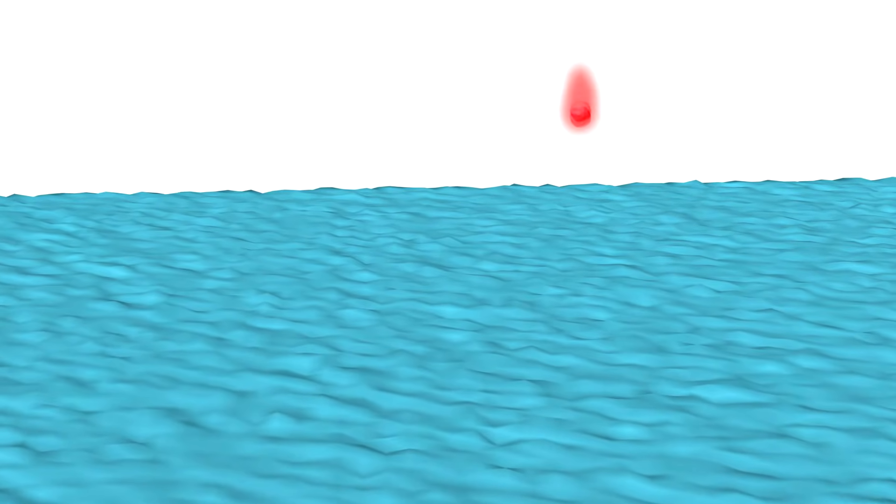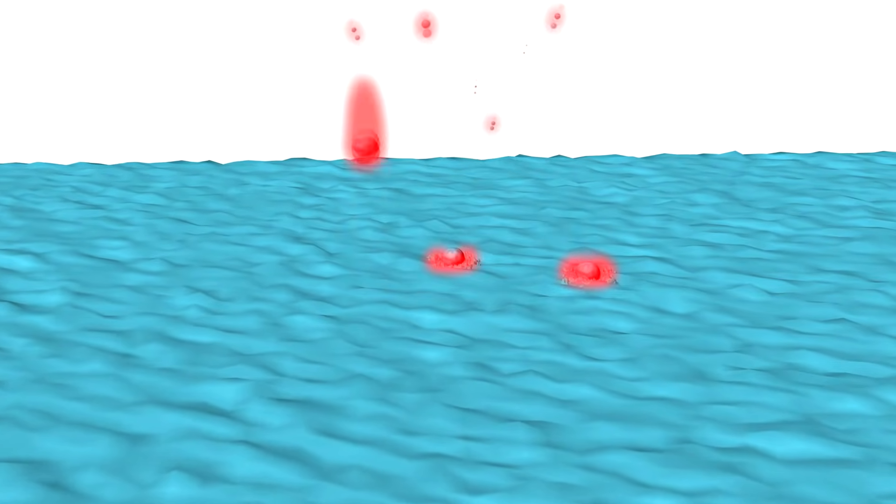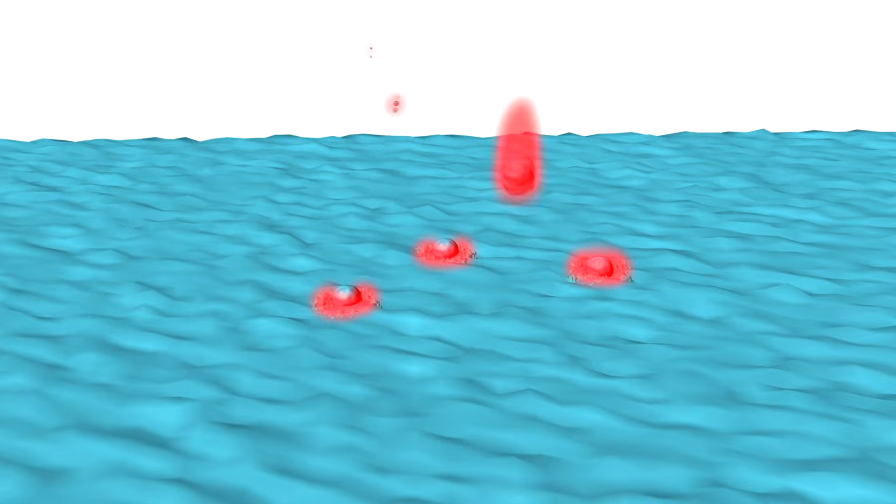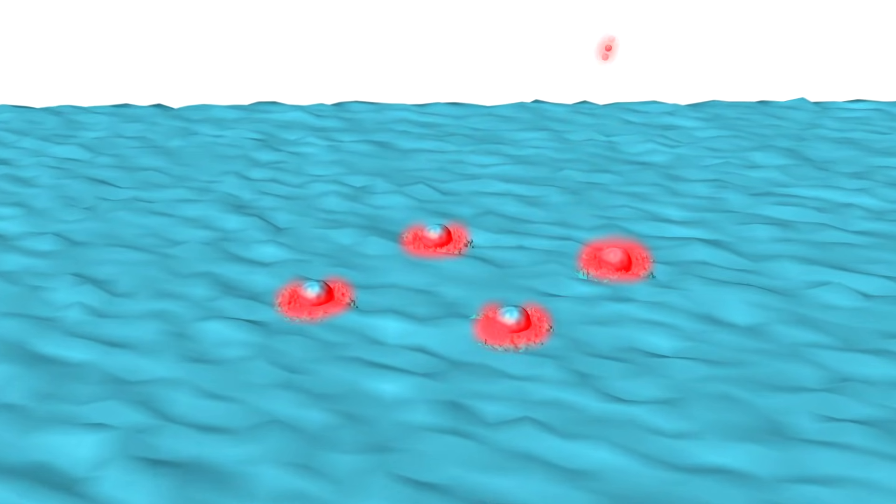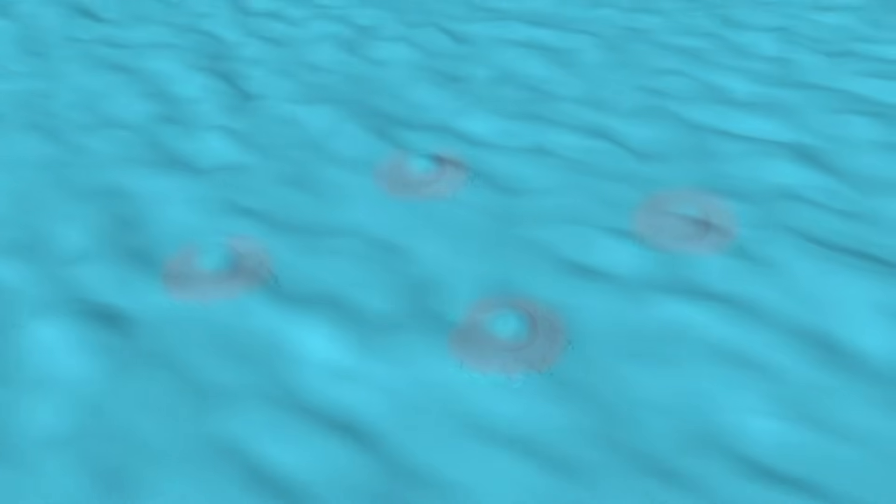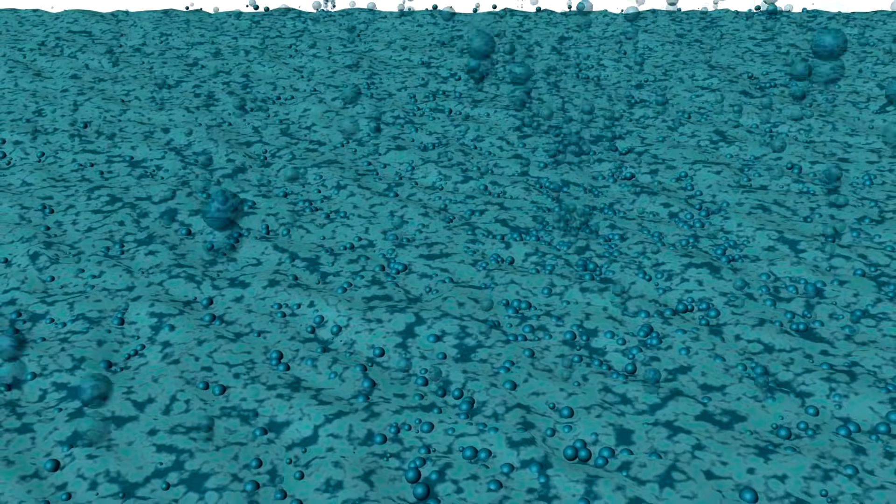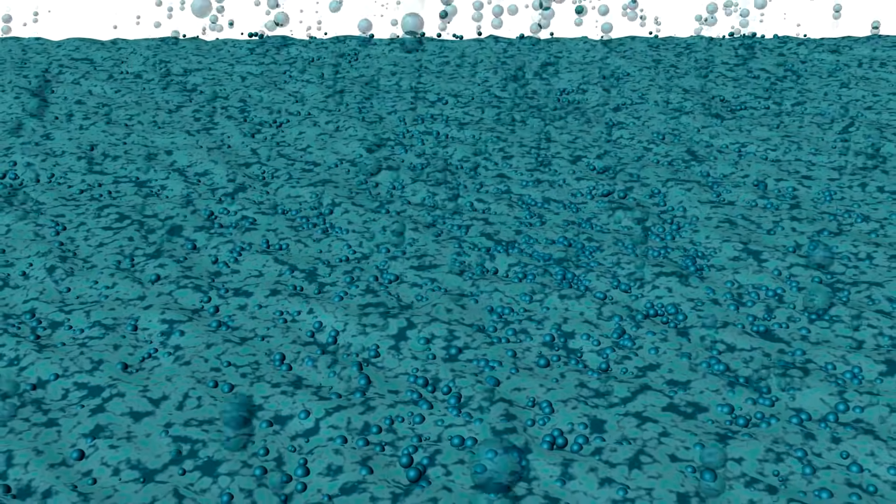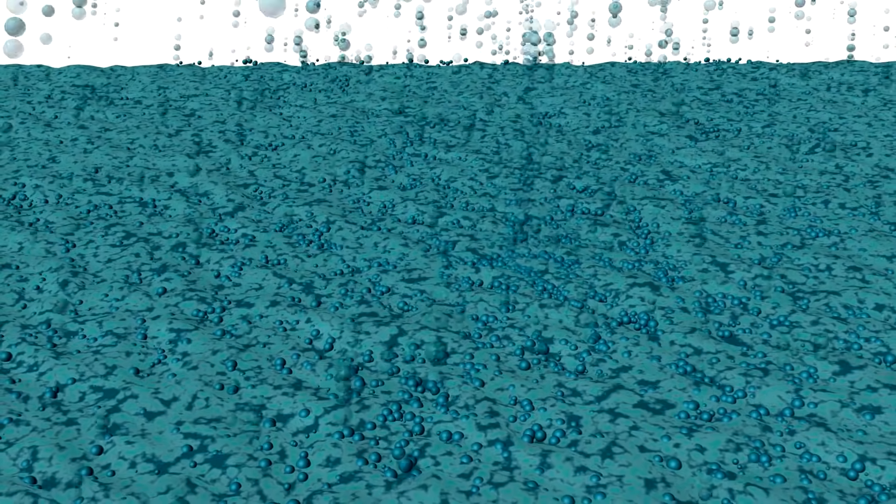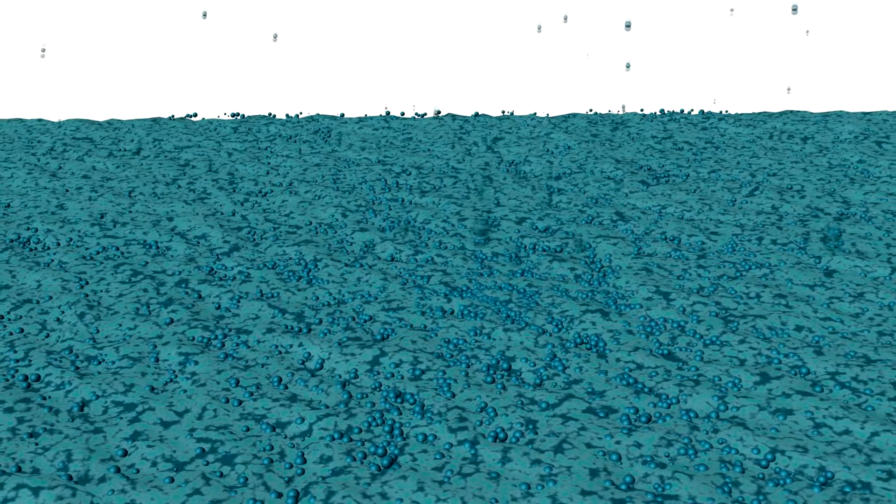At lower pressures, the extracted particles are not slowed down and they hit the substrate with a higher energy. This may cause localized damage and sputtering of the previously deposited film. However, when the gas pressure is too high, then the energy of the atoms arriving on the growth substrate is not high enough to allow the formation of an ordered crystal structure. The resulting film may be with low density and amorphous, which in some cases may be the actual goal.